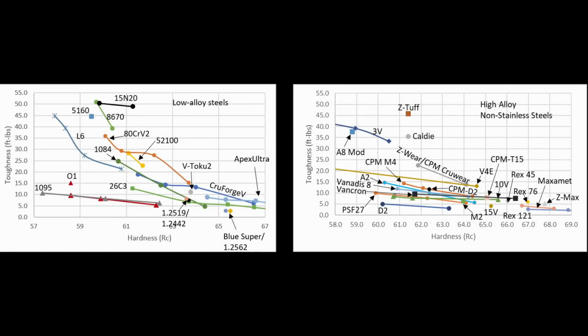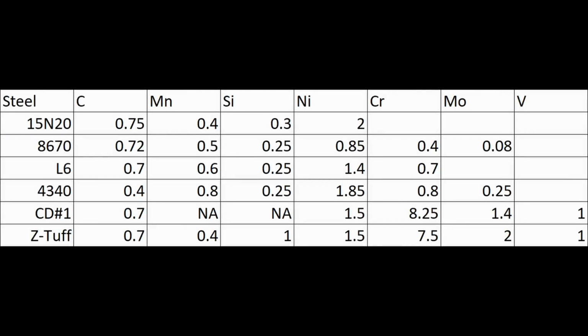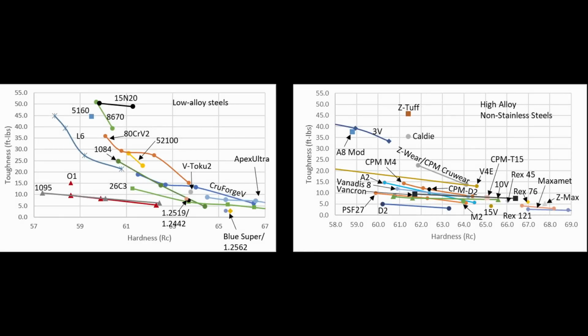Okay, so to summarize, nickel is a great element for improving toughness. 15N20, 8670, and Z-Tuff in particular are the highest toughness steels I have tested, and each of those has a significant nickel addition. Of course, their toughness is also helped out by the fact that they are all 0.7% carbon steels and they have very little carbide, but they do have excellent properties in that 59 to 61 Rockwell range, maybe a touch harder, where you need really high toughness.